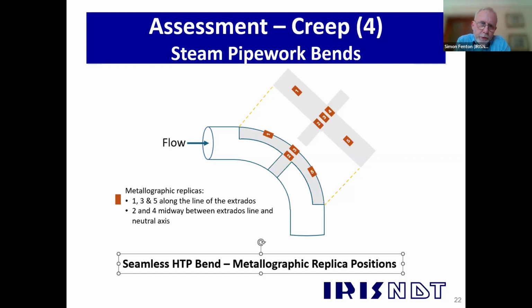The NDT is also carried out in a band all the way along the extrados, but also all the way around the circumference of the bend at that midpoint, capturing the intrados of the bend as well as the extrados. And this was based on that previous slide I showed you, where not only did we suffer creep damage on the extrados, that was the worst damage, but we also found creep damage starting to develop at the intrados as well. So we, as a precaution, apply MPI and UT to all of those areas shaded in grey on that slide.